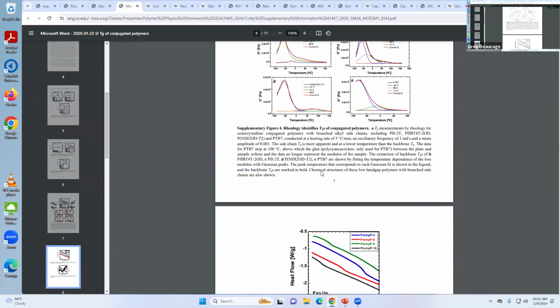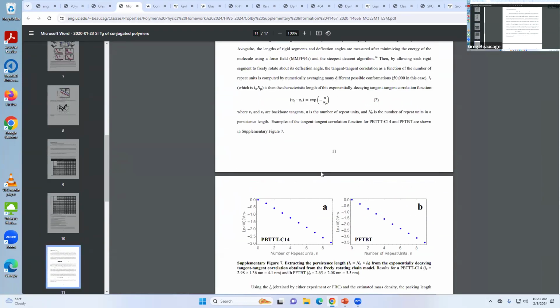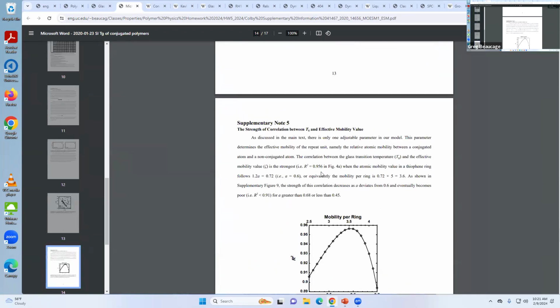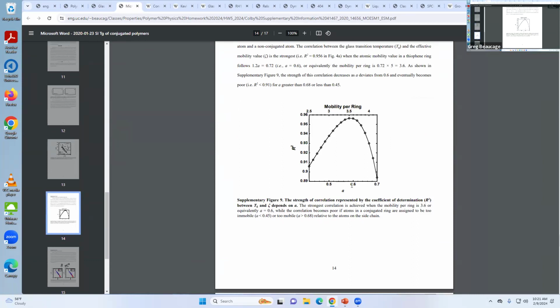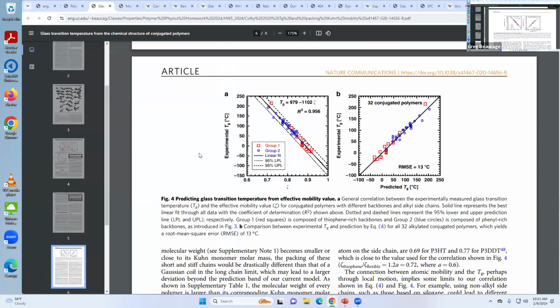So they have the A parameter here somewhere. What they do is they write an equation that's got to do with the structure. It has only one free parameter A. Then they change A from 0.4 to 0.7. And then they find the mean square difference between the TG that they predict and the TG that the material actually has, right? And they find there's a sweet spot around 0.6 for A. And with that, they can predict the glass transition. Using that A in their equation, they can predict the glass transition almost perfectly for all this slew. Each dot here is a different material, right? So that's kind of sweet.